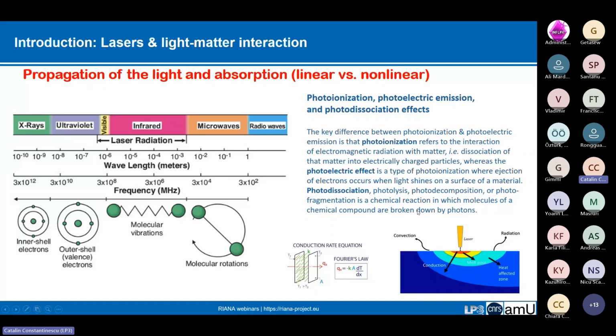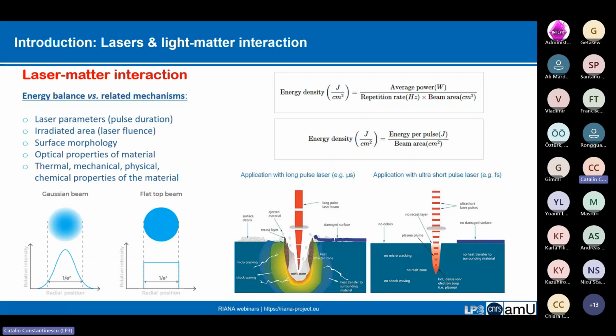All these effects must be considered together in the global laser-matter energy balance. The processing outcomes depend on a delicate balance between the laser parameters, the beam profile, the surface morphology, and the intrinsic material properties. These are really important. Pulse duration is especially critical. The laser I mentioned before, the ytterbium YAG, is actually a tunable laser, so we can tune from picosecond to femtosecond and back. So let's now move from fundamentals to additive laser processing.